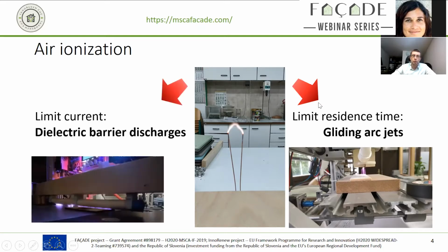A different way to create this is so-called barrier discharges, where you simply place an isolator in between the contacts. The air will still ionize, but you won't get the formation of an arc, and so it's not going to get hot. And this is something that's also very common for treatments of substrates. Like in this case, there's a wooden slide lying just on the table, and above, the white tube is the isolator wherein the electrode is provided.